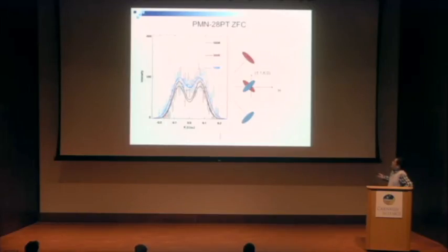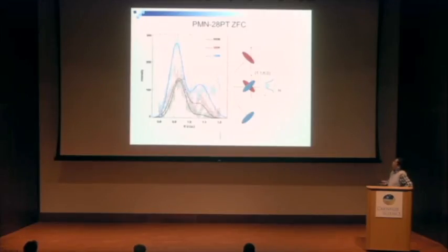From this scan direction, the left peak is always from the red wing, and the right peak is always from the blue wing. Near the 110 Bragg peak, the peak from the red wing is much stronger, but there is still some intensity from the blue wing. And near the 1-10 Bragg peak, the situation is similar, but the opposite way.